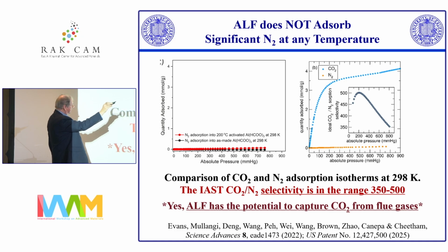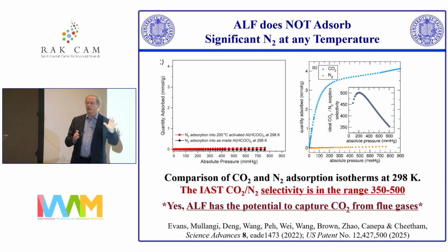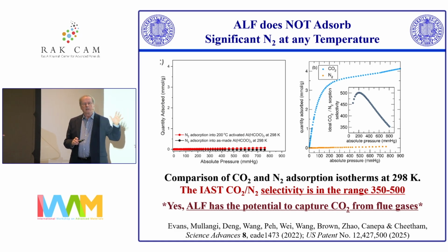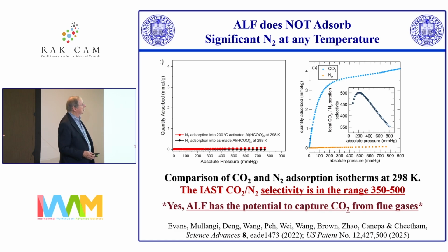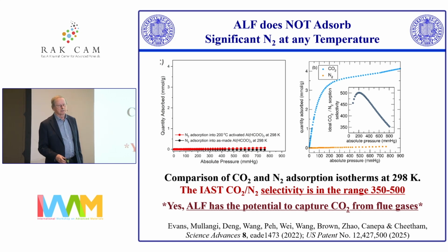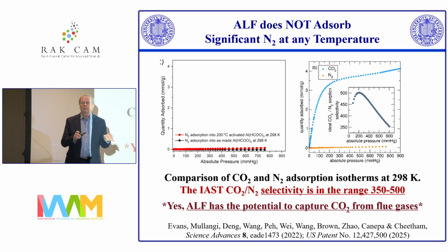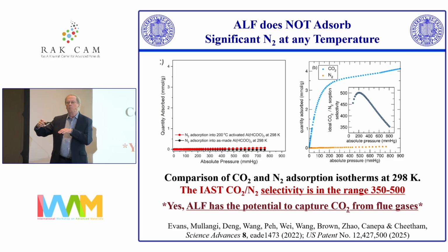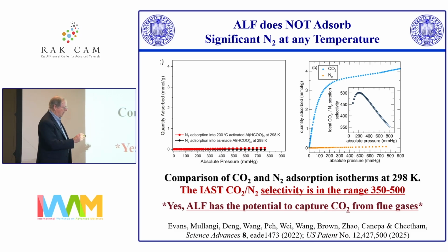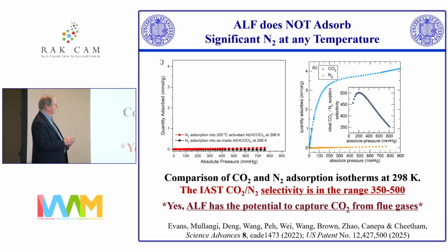And so we have a selectivity of CO2 over nitrogen of 400 or so. This is the IAST selectivity that you do from the single gas isotherms. But it's incredibly selective for CO2. And so it does have the potential to capture CO2 from flue gases. However, like most other MOFs, ALF is not stable in moist atmospheres if you take it significantly above room temperature. Say, take it to 50 degrees C, and it starts to fall apart. And we understand the chemistry of that quite well, but it's a serious problem.